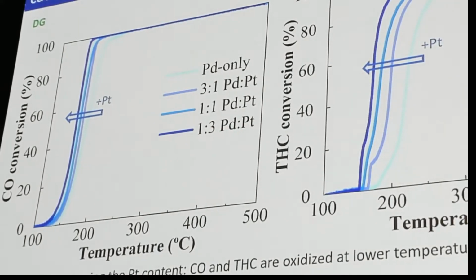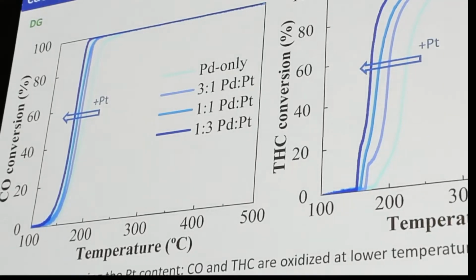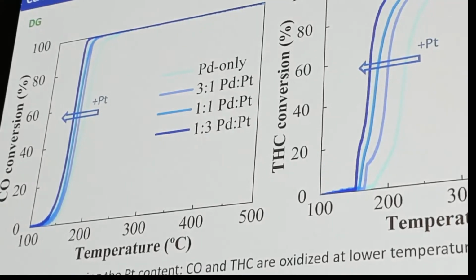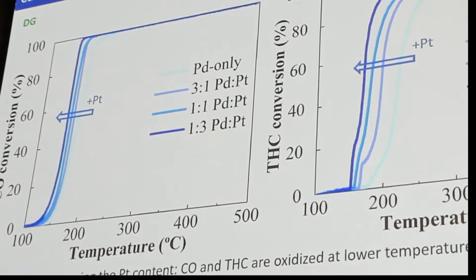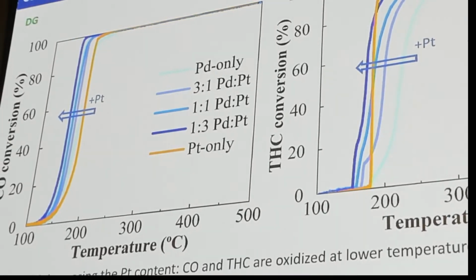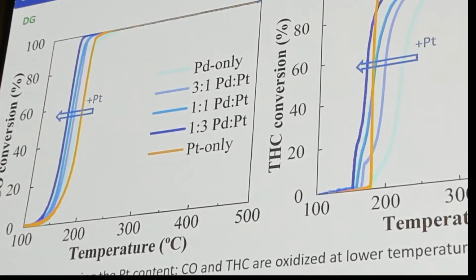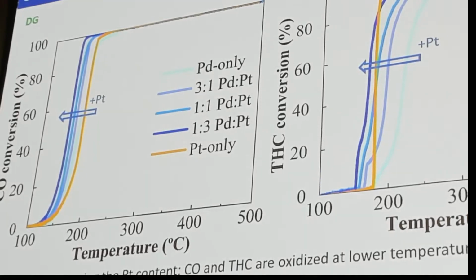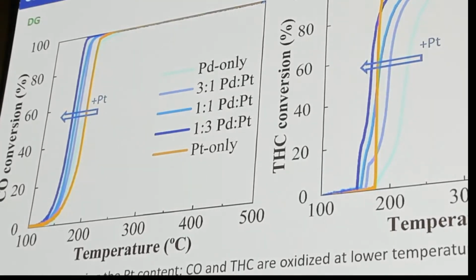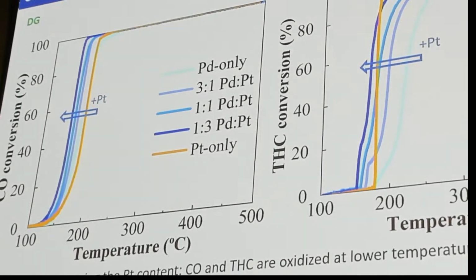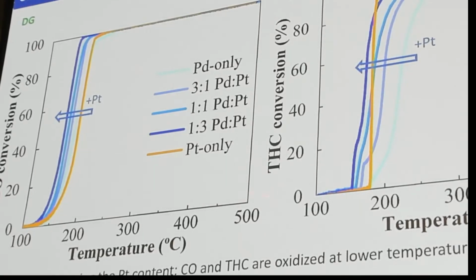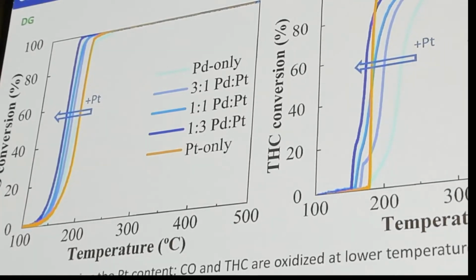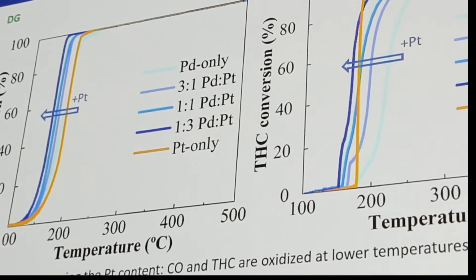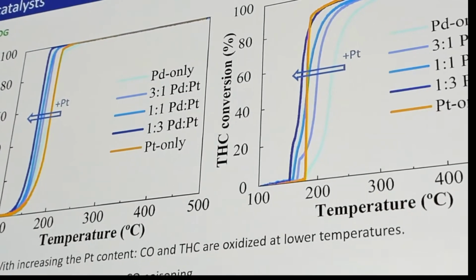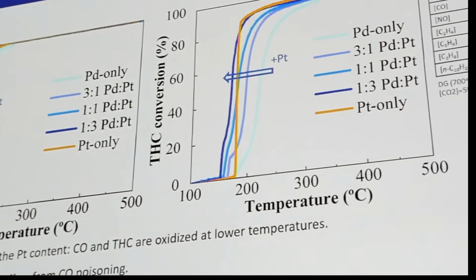Of course, some of you might be wondering, well, why don't we make a monometallic platinum catalyst? This might perform even better. So we did that, and here you can see the performance of the monometallic platinum in yellow. So you can see definitely the bimetallics perform better than the monometallic platinum, and again, the 1 to 3 ratio of palladium to platinum seems to perform better than all the other catalysts. This is the degreened performance.